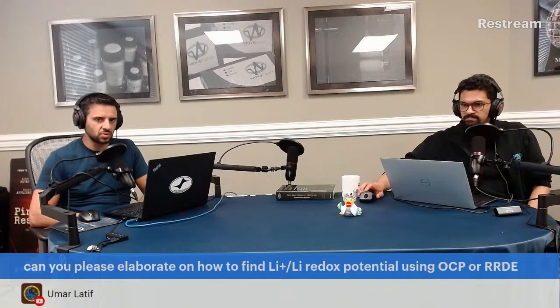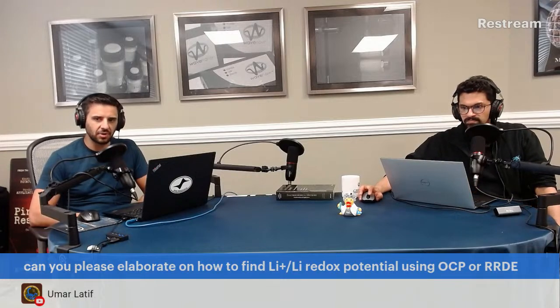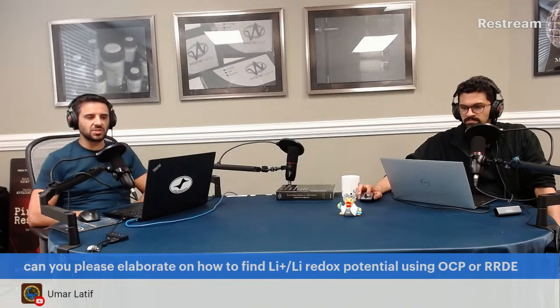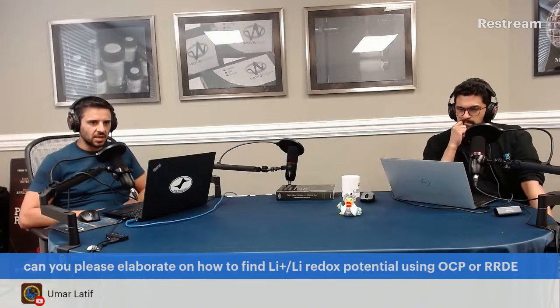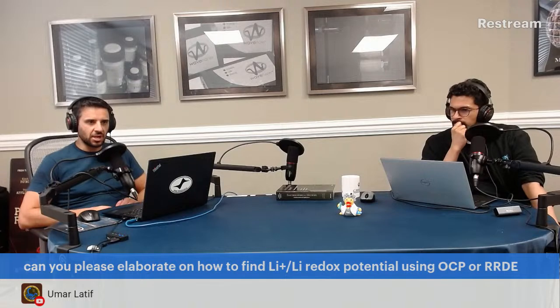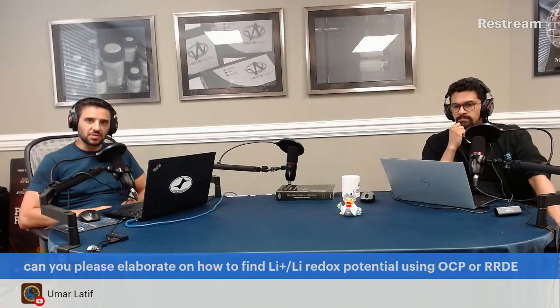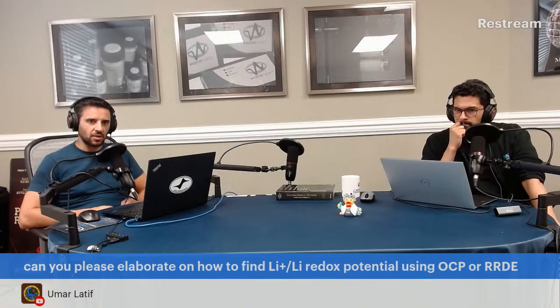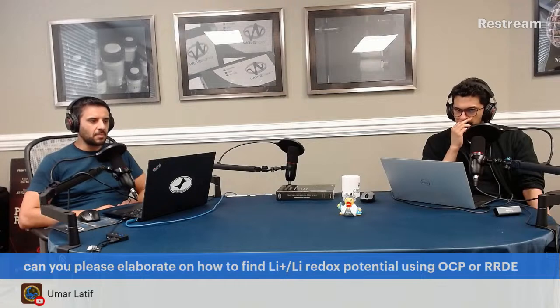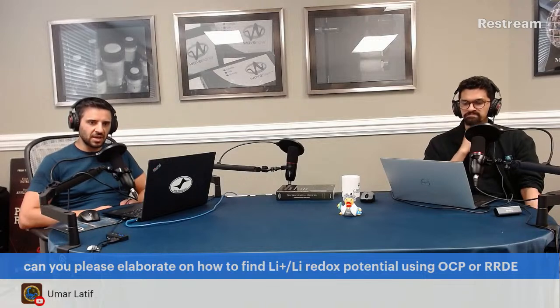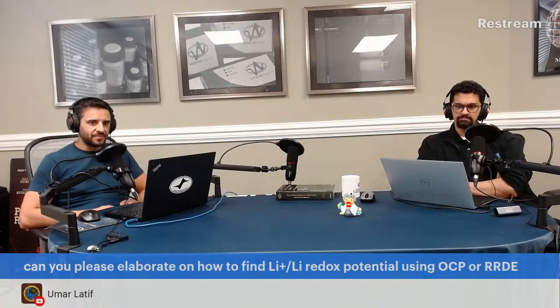So you would set up a very small 3 electrode system with your active material, or you'd construct a coin cell. In fact, that's a lot of times a better way to do it. If you're studying an anode material and you want to find its redox potentials, where it intercalates or alloys or converts lithium, for charging and discharging, or a cathode, either way, you would construct a cell with lithium metal as the other electrode. Whether you're doing cathode material, lithium metal as the anode. If you're doing an anode material, lithium metal as the cathode.